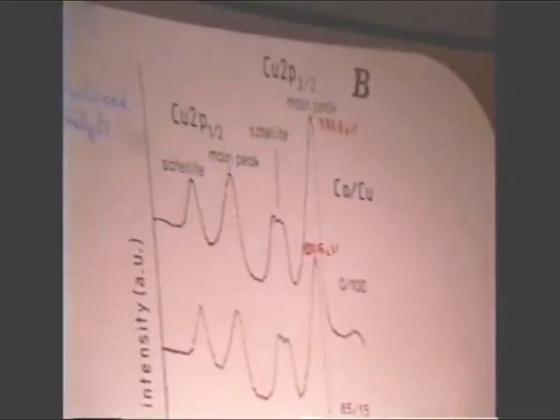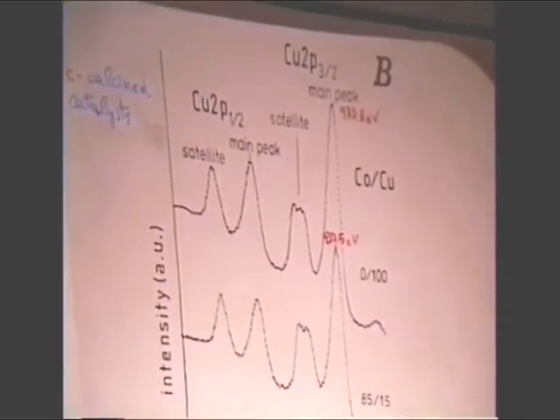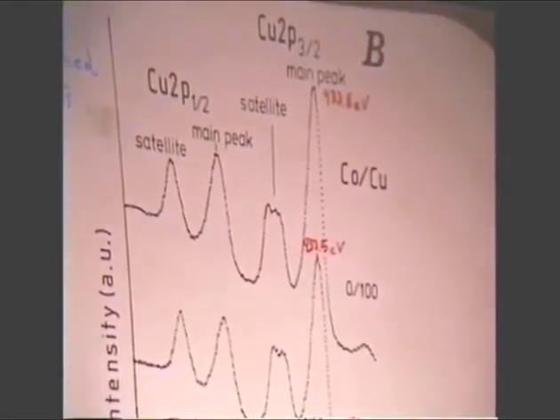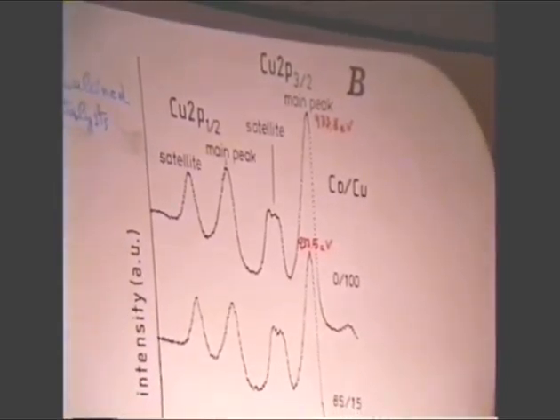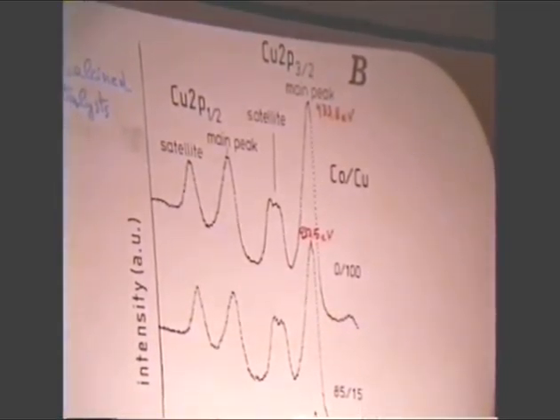The situation is much different for the air-calcined catalyst, and as you can see, there is a rather intense satellite peak, and the main peak in this case was fairly symmetric. This suggests that for the air-calcined catalyst, mainly copper 2 plus species are present, and this is also in agreement with the bulk results.